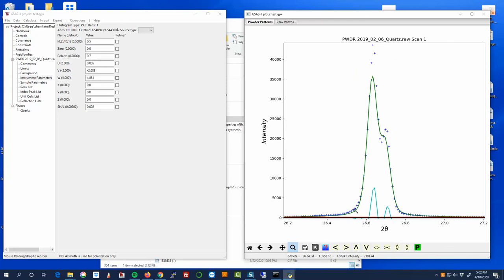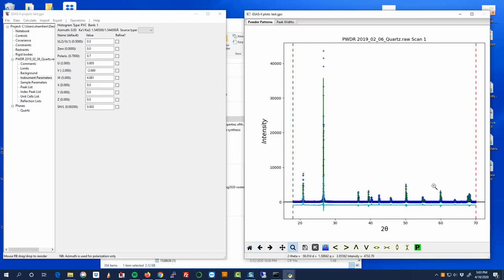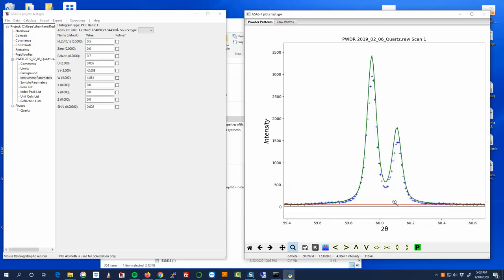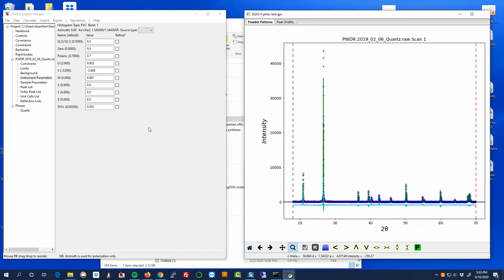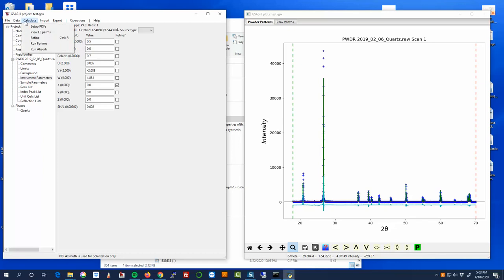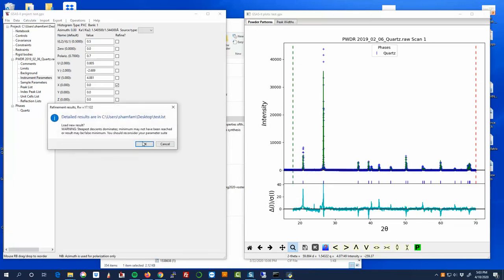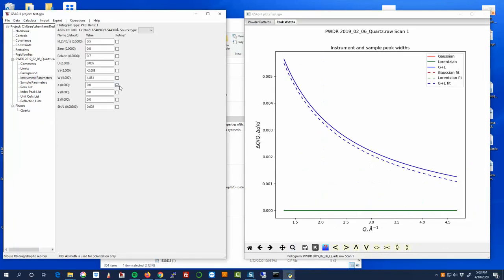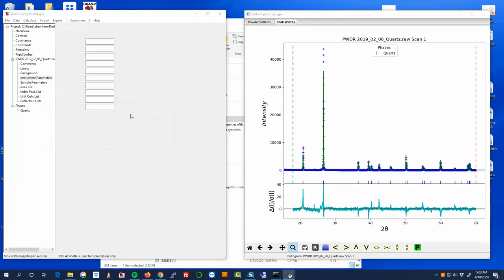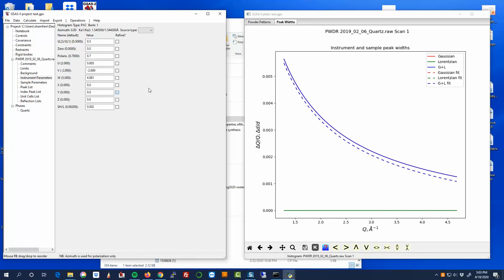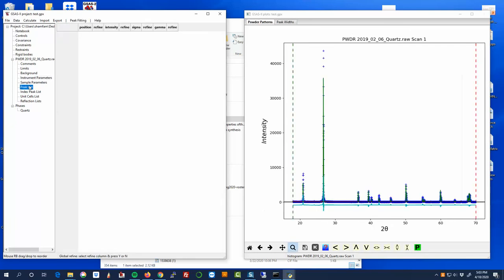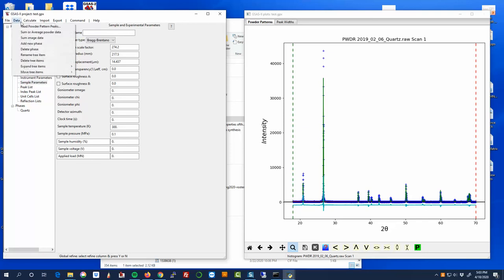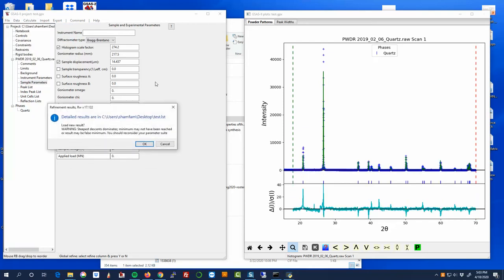So I'm actually going to turn these off. Let's come back to our powder pattern. And if I look here, you know, our tails still aren't quite right. And it turns out the Lorentzian component is more important in the tails. So the Lorentzian part of the function can contribute some significant intensity to the tails. Let me look up at a different higher angle peak just to see the same thing. But that might not totally solve it. So in this case, I just have the intensity is higher than the observed data. But there's nothing wrong with at least giving it a shot in terms of looking at what happens as we start to refine LX. That didn't seem to have too much an effect. So that's not actually changing things, I think. So I'm going to leave these here. I'm going to go back to sample parameters, turn displacement back on. And we'll run the refinement one more time just to be thorough.